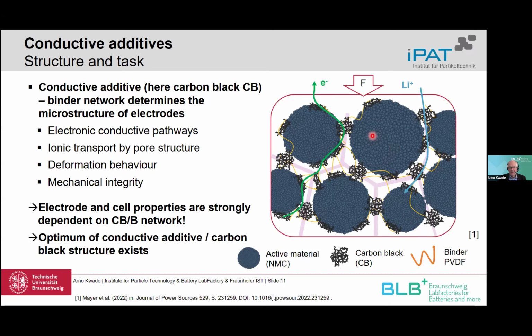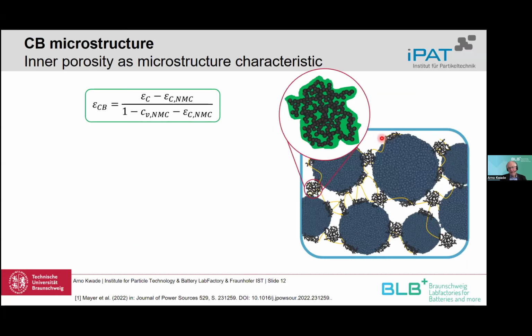And that we have to have a really intensive focus on this carbon black binder network, which is between the active material particles, which are shown here as cathode particles, polydispersed particles. Today we also use so-called single particles besides these polydispersed particles, which is only one particle. It's not an agglomerate like the typical polydispersed ones, but this is a topic which we maybe don't focus on too much today. As I said, the inner carbon black porosity we found is a good measure also for the structure. It also is the case that the smaller the agglomerates, the smaller also the inner porosity, because the agglomerates break where the porosity is the largest.